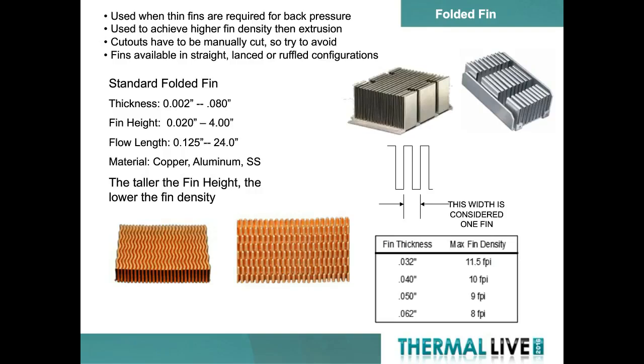Just like an extrusion, there is a limit to the aspect ratio on these. As the height of the fins get taller and taller, the tooling requires the fins to get further and further apart. This can be overcome with some alternatives that I'll show in a couple of minutes. Like a bonded fin, the fins are separate pieces from the base. They need to be attached either with a solder, an epoxy, or a brazing operation.